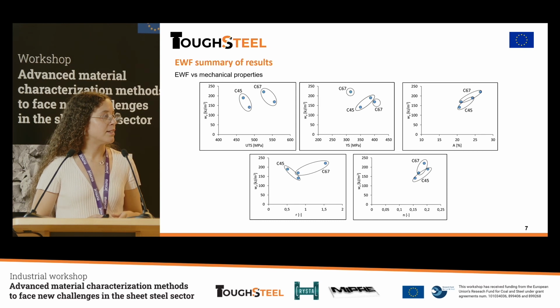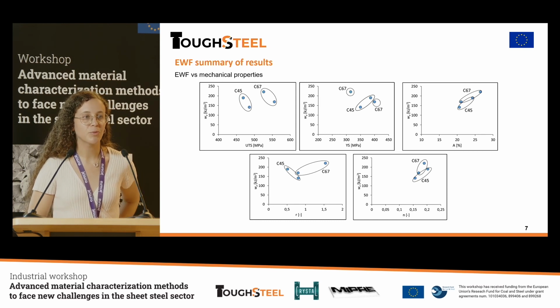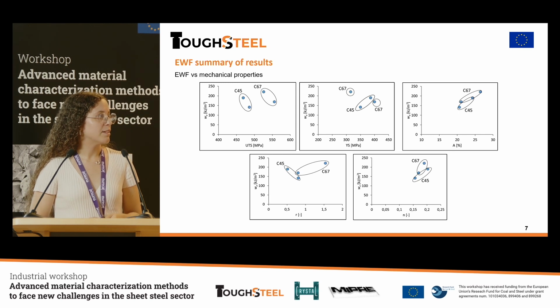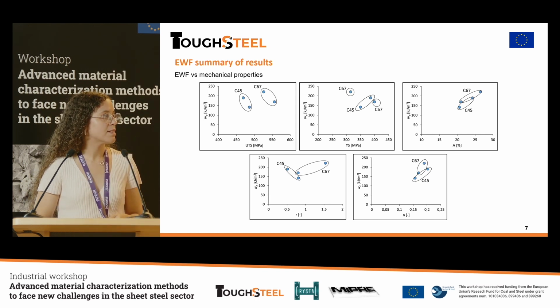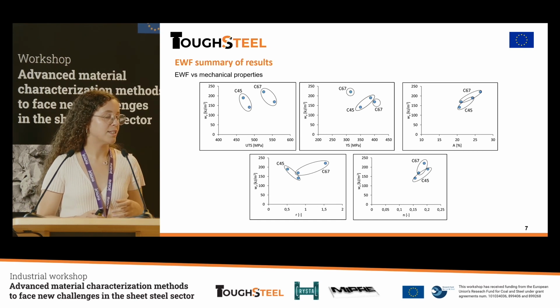Later, we could relate these essential work of fracture parameters with the mechanical properties, and we could find some different tendencies. For the UTS, it was decreasing with the essential work of fracture. In the yield strain, the tendency was different between the 2 materials. The elongation was higher, mostly when increasing the work of fracture. And for the anisotropy, we have a different tendency in both materials, and for the n value, it was increasing, although it was not expected to find this correlation.